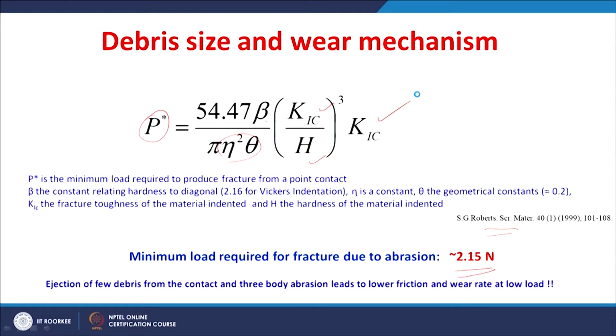Once this material is removed as debris, the debris are trapped in the contact and a few of them may be ejected out of the contact. That leads to a lesser coefficient of friction, and because of the debris in the contact, it is actually a three body abrasion. In three body abrasion, these particles can roll easily, so it gives a lesser wear.